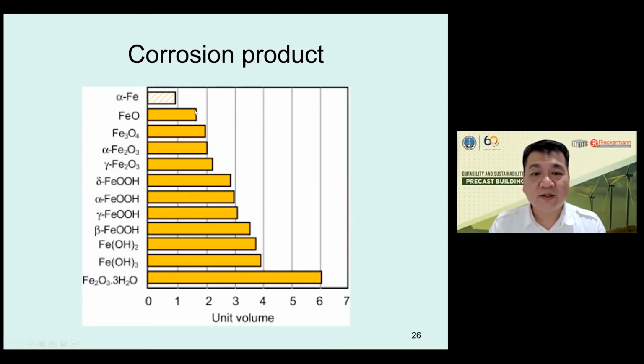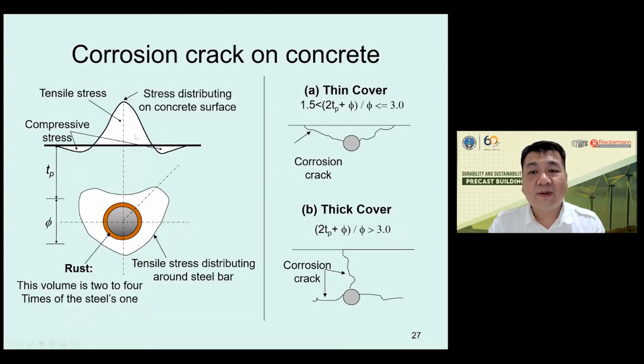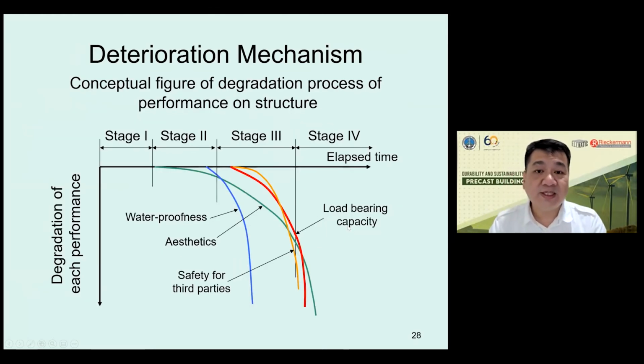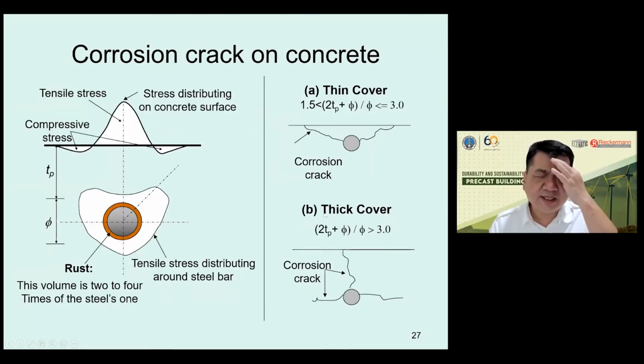So this is actually the cause of why the concrete spoils, why the concrete is cracked, because of the expansion of the rust. When the corrosion starts, the rust will expand, and then our concrete will have tensile stress. And when the tensile stress is higher than the tensile strength of the concrete, it will crack. And the cracking has two conditions. One is the thin cover, it will spoil, and the thick cover just cracks, and the rust will come out from that part of the concrete. So we see the basic of deterioration is like this.